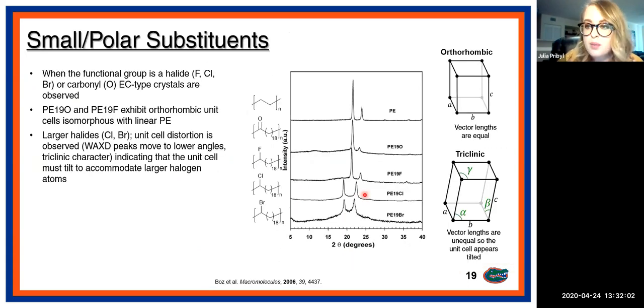The second system that I want to talk about is, what if we now keep the substituent small, but introduce polarity. So when the functional group is a halide, like fluorine, chlorine, or bromine, or carbonyl, we also observe extended chain type crystals because they're small enough to be included into the crystal structure. I have over here a wide angle X-ray scattering pattern of different polymers that are prepared. The polymer structures are here on the left for each trace.